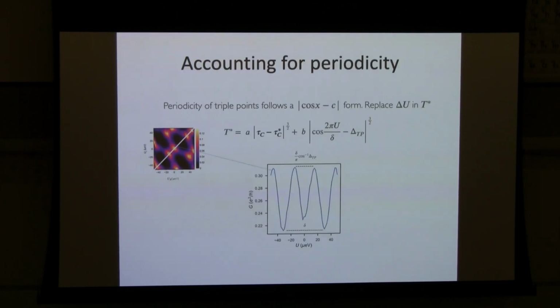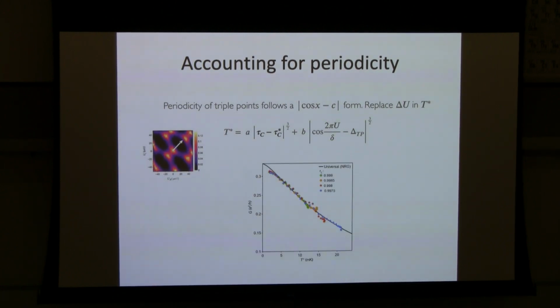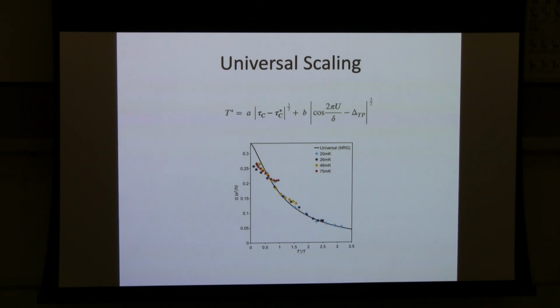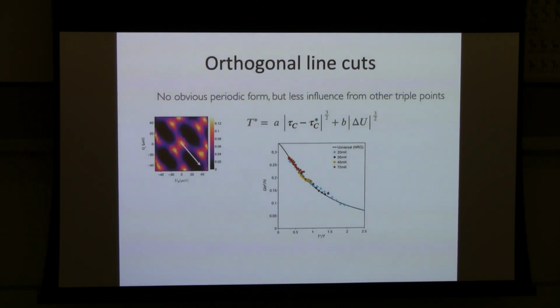It turns out that deviation is because we're cutting along this line, and when you go too far, you actually come close to the next pair of peaks where you can add more electrons. And so if you make a correction for this that other theorists suggested, then you find that actually it falls along that line. It even does somewhat better if you move away from this special point in another direction.